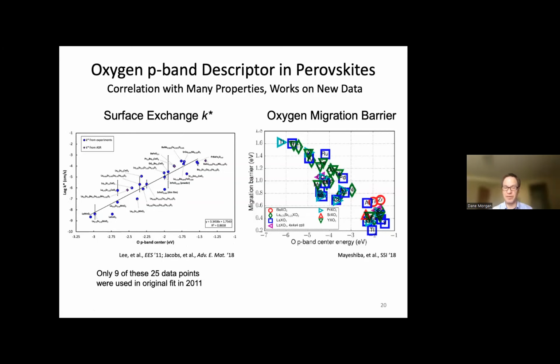And actually, he first realized that in 2011, and he had 9 data points. Since then, we've collected another 16 or so data points and added them to the plot, and they still fall on a line. So that shows that we didn't just make it up by cherry picking our favorite 9 data points. Over the years, every time we add a new data point, it generally falls on this type of correlation.